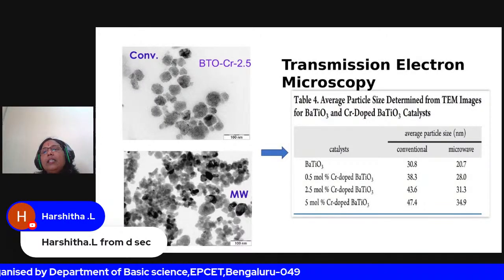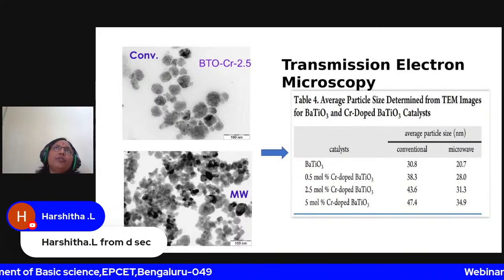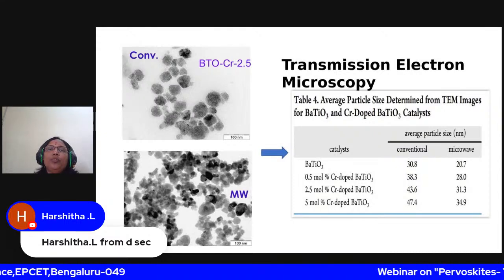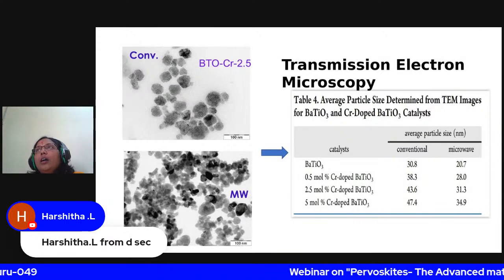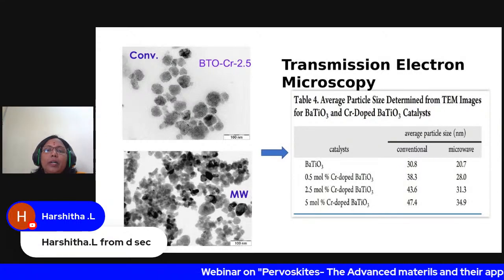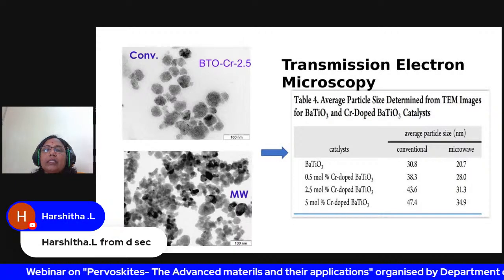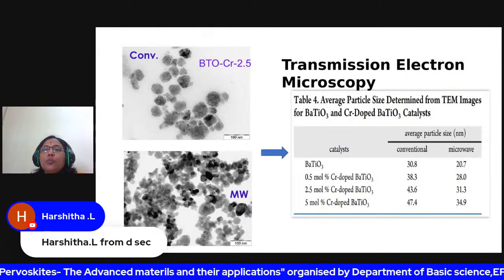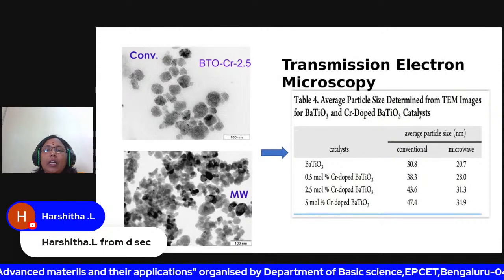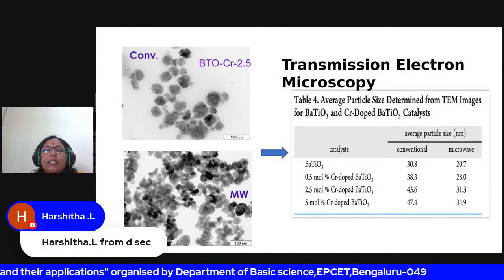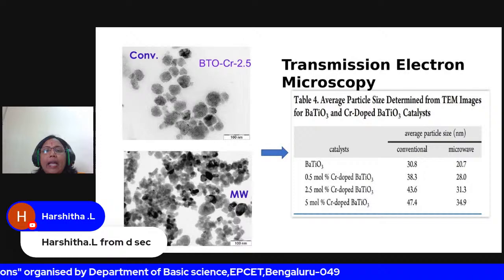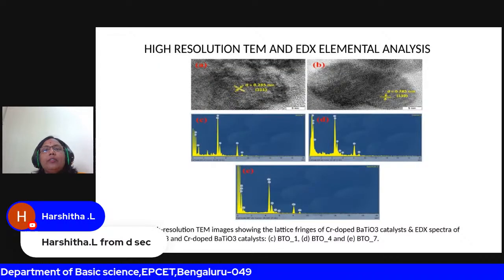So this particle size is within 0 to 100 nanometers, so we can declare this as a nanomaterial, but not the bulk material. And the particle size of the microwave synthesized material is very small compared to the conventionally synthesized material. Let's see whether it has an effect on catalytic activity or not.